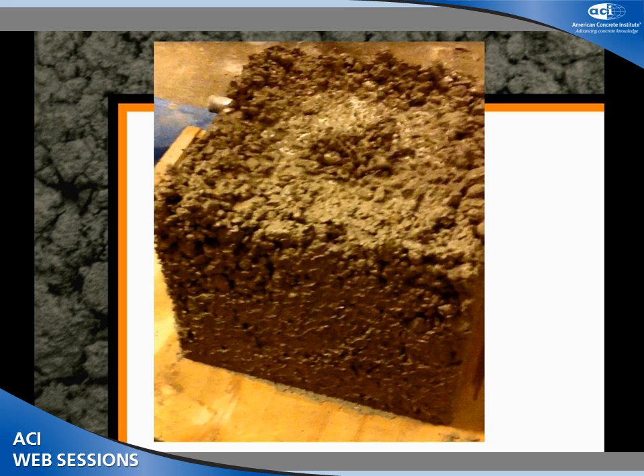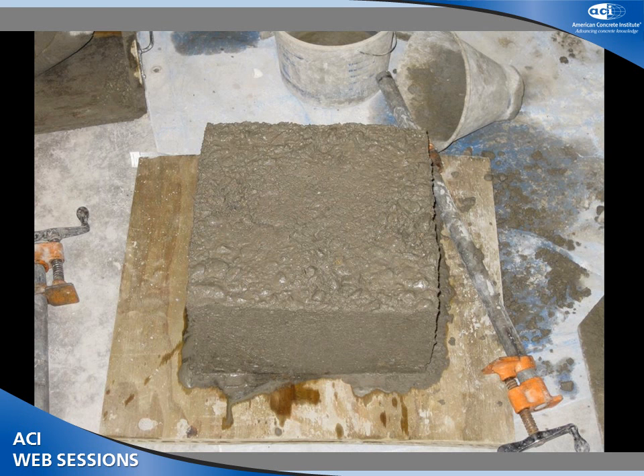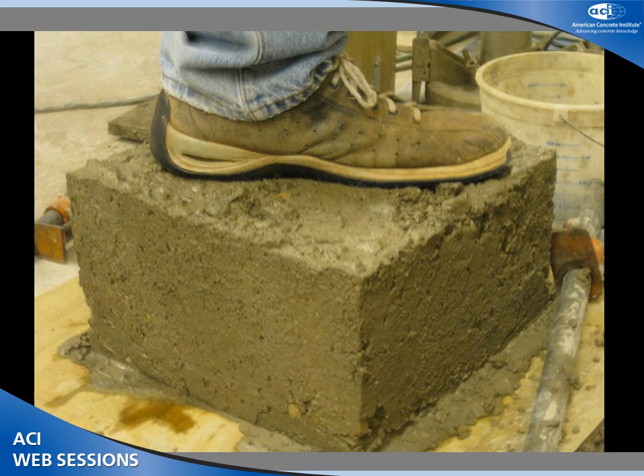That's what it looks like once you drop the edge of the box off — lots of holes. That's a failed box test. This is one that passes — it's like a beautiful concrete brownie — no holes on the side. And the best test: I can stand on it, one foot on top of the concrete. This is 10-minute-old concrete holding me with no slumping.